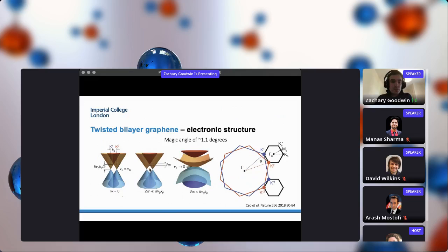So when we twist the angle by a very special twist angle, which is referred to as the magic angle, which is around 1.1 degrees, the momentum misalignment between these 2 Dirac cones matches the hybridization energy, and we get the emergence of extremely flat electronic states near the Fermi energy.